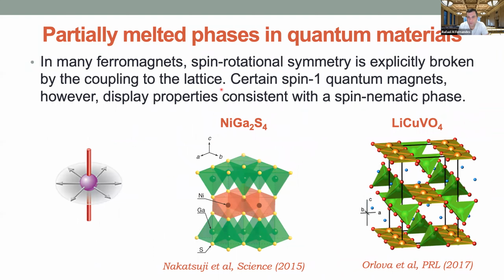One of the problems is that once we have a crystal, spin rotational symmetry is explicitly broken because of the lattice. But there are spin-1 quantum magnets where, because of the quantum nature of the spins, you can actually have a property equivalent to a spin nematic phase, and there are signatures consistent with a spin nematic phase in these materials.